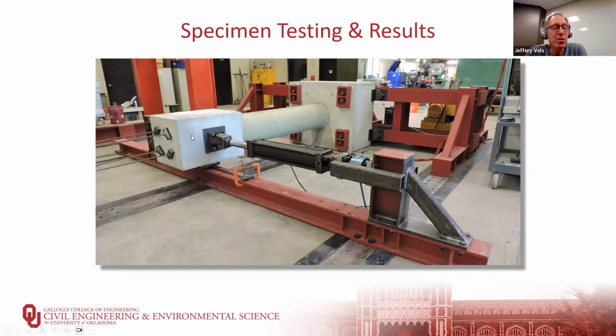On the backside of the loading stub at the same location as the ram, we have a wire pot to measure the displacement of the top of the column. We have another wire pot on the other side of the column at about mid-height. We also have 2 wire pots on the back side of the base of the specimen in order to measure any rotation in the base.